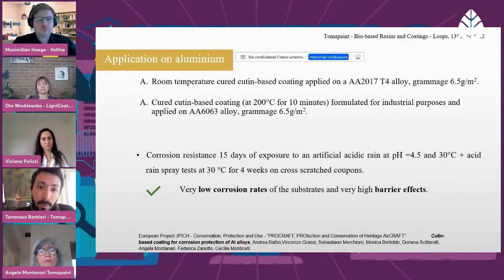The University of Ferrara developed two formulations of cutin-based lacquer to coat aluminum alloy. The first formulation was cured at room temperature, the second one at high temperature, and the results of the study highlighted that the application of cutin-based lacquer to coat AA2017 T4 aluminum alloy sheets at a grammage of 6.5 grams per square meter gave a high corrosion resistance after 15 days of exposure at the acidic pH at 30 degrees.